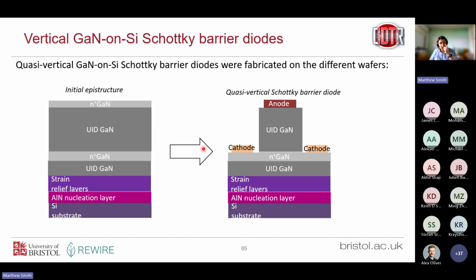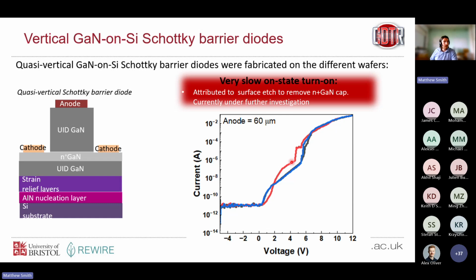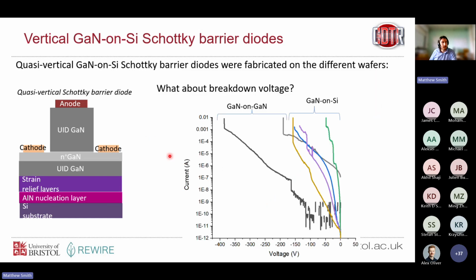These are quasi-vertical devices. So earlier I said you have to etch through the substrate and all these layers here. To get around doing that initially, we made these quasi-vertical devices where the current path is vertical, but we put our cathode to the side here off a mesa. So we do have quite poor turn-on characteristics here in these quasi-vertical devices. That's still under investigation. We think we know the reason, but we're currently working to investigate that.